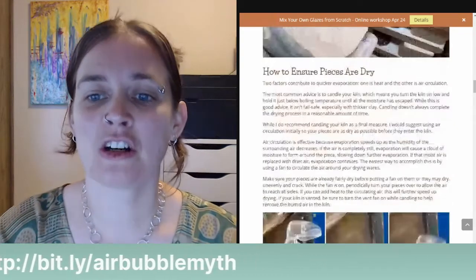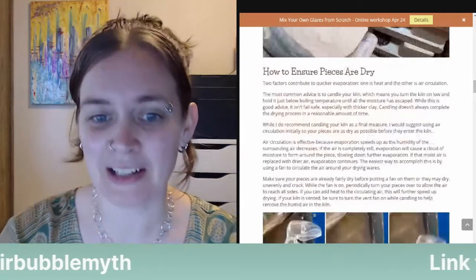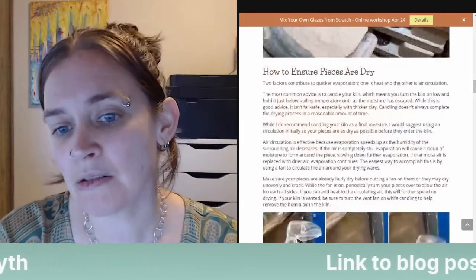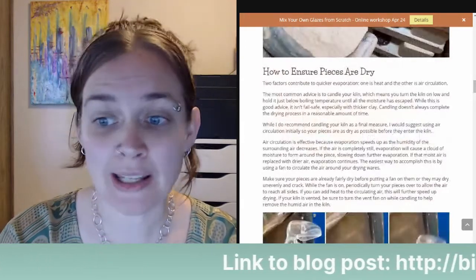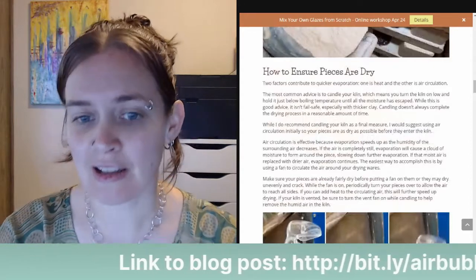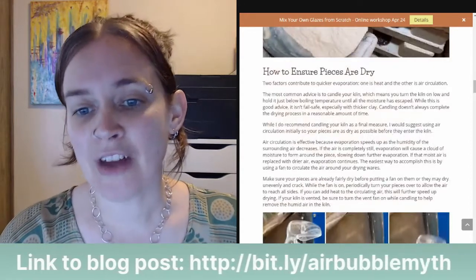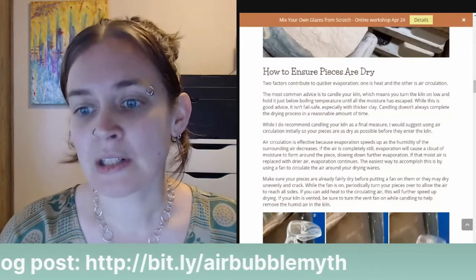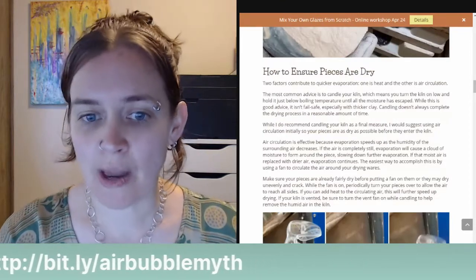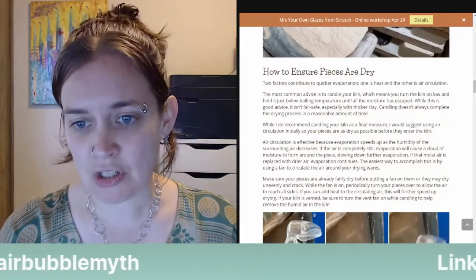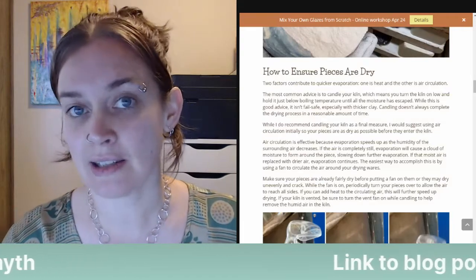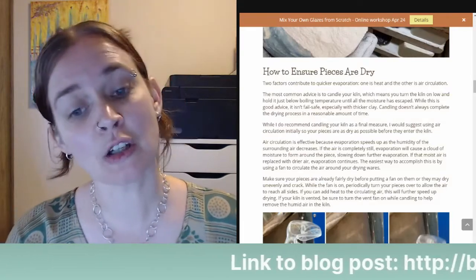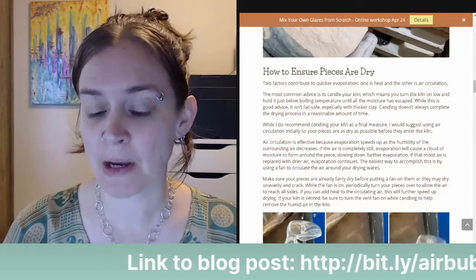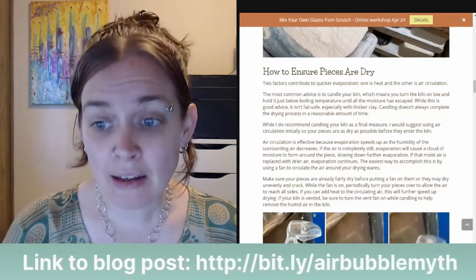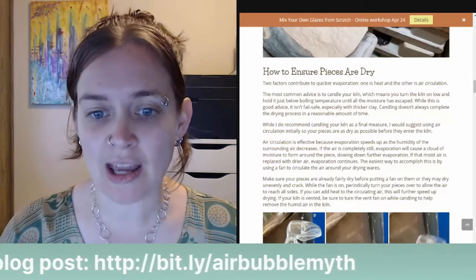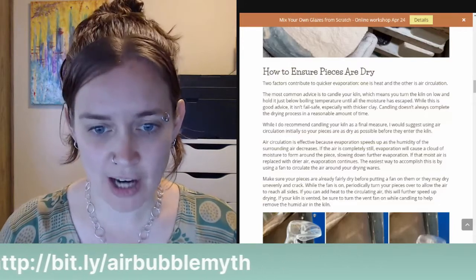So how to ensure pieces are dry. Two factors contribute to quicker evaporation. One is heat and the other is air circulation. The most common advice is to candle your kiln, which means you turn the kiln on low and hold it just below boiling temperature until all the moisture has escaped. While this is good advice, it isn't fail-safe, especially with thicker clay. Candling doesn't always complete the drying process in a reasonable amount of time.